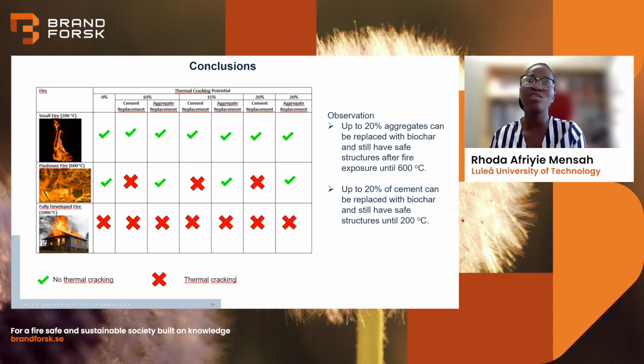for 10, 15, and 20% experienced thermal cracking, but the aggregate replacement and the standard concrete did not experience any cracking. But when we consider the large fire or the fully developed fire at 1,000 degrees Celsius, all the samples experienced thermal cracking. So from this, we can make conclusions that up to 20% aggregates can be replaced with biochar, and we can still have safe structures after fire exposure until 600 degrees Celsius.